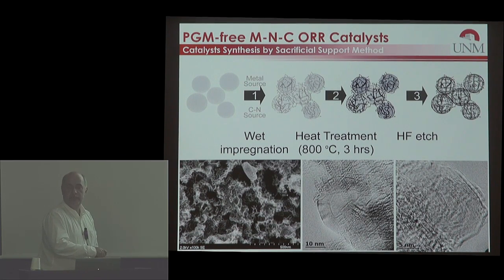So in the process of this pyrolysis, what happens is that the silica particles leave the building, being responsible for the mean pore size in the mesoscale, because that's how we choose the silica. But there is actually also smaller porosity in the walls that is formed by the departure of gases. And the majority of the carbon is in a turbostratic formation, while some parts of carbon are highly graphitized, and one can hypothesize that they're highly graphitized because they formed around a remaining metallic iron that at the beginning was in the matrix, but later was etched by the hydrogen fluoride.